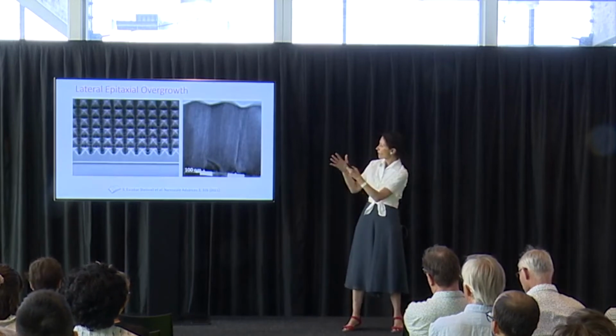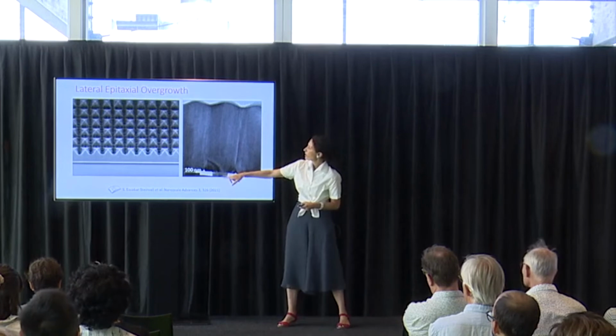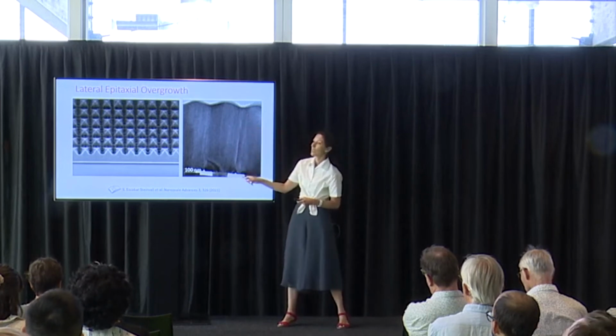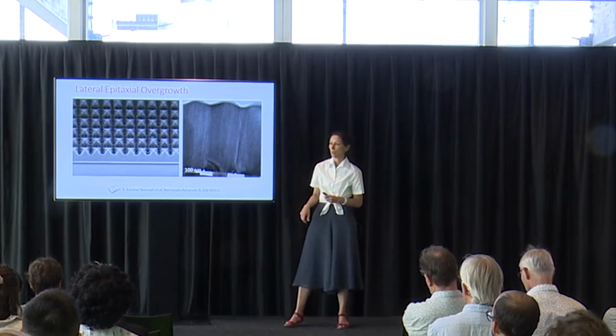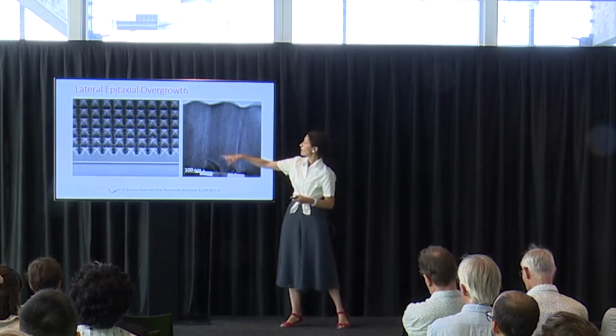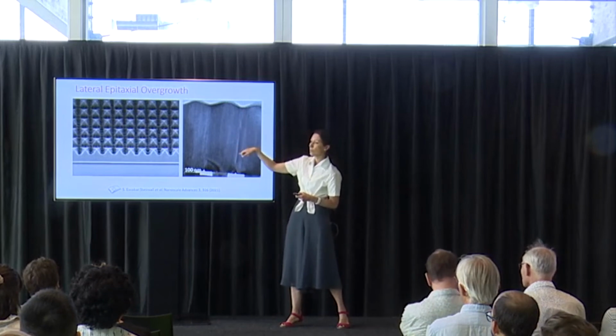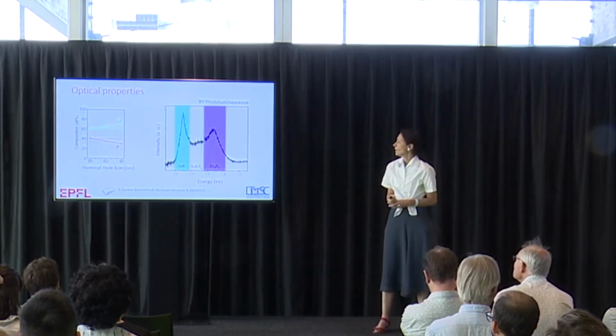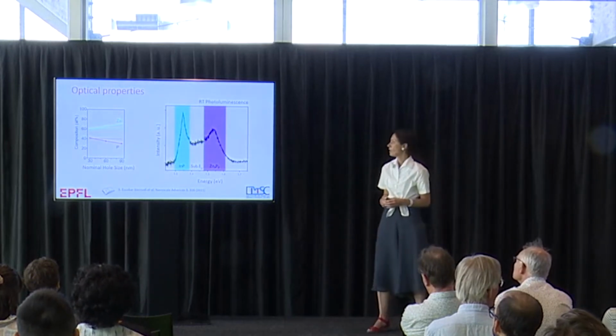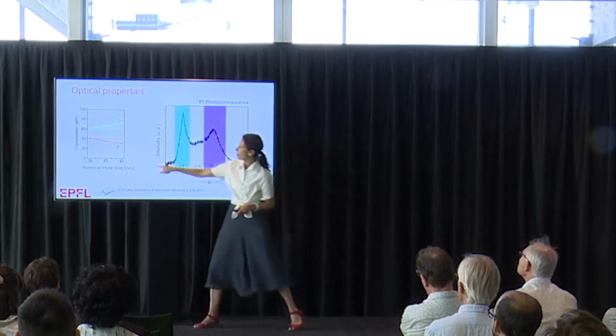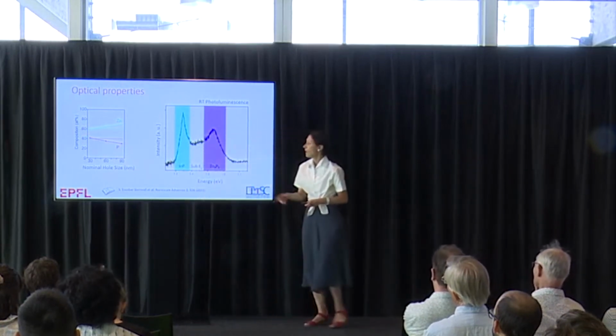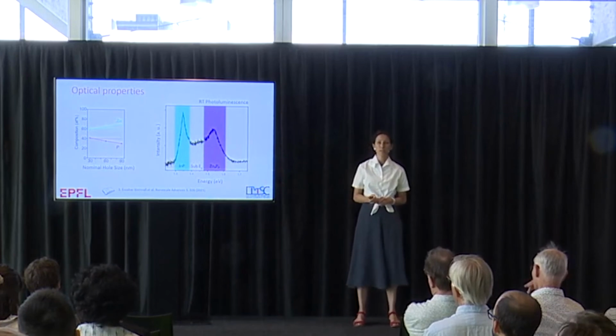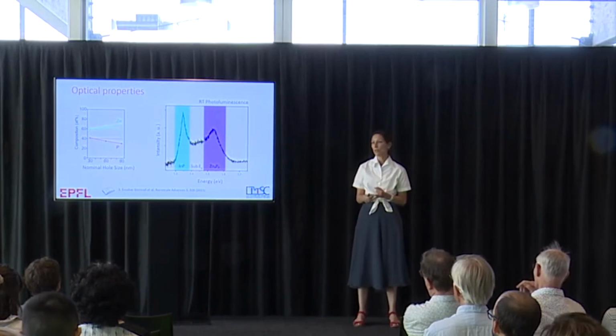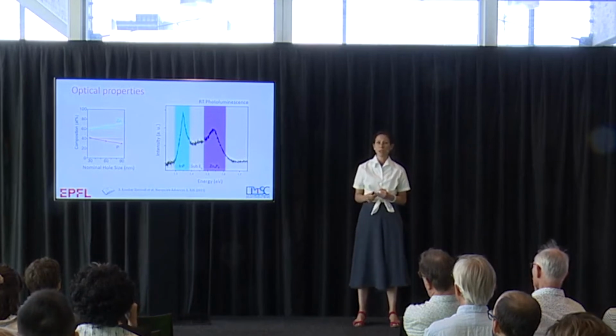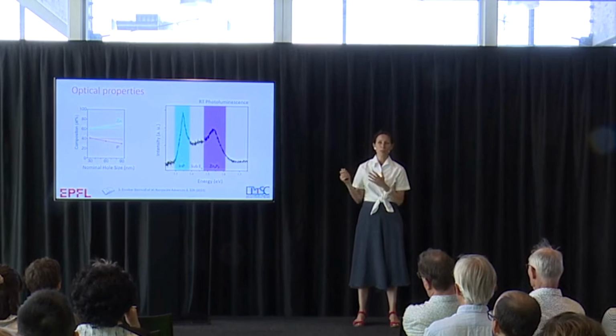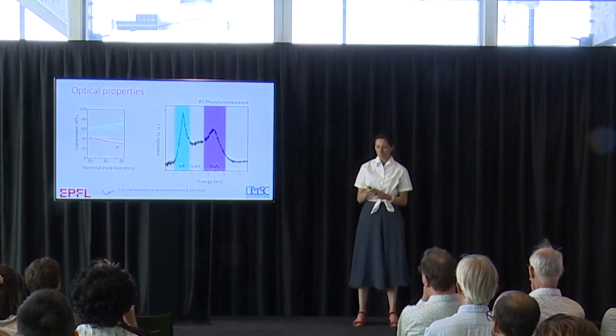If you look at these joined structures, you see that the grain that starts here is single crystalline. You have some grain boundaries here. We think it shouldn't be too much of a problem because the carriers that you recombine have to go through this path and should not come to the grain boundary. Now, if we look at the properties of these materials, we can also change the stoichiometry, as you see here, depending on the size of the hole, and they have room temperature luminescence. The nanowires only have low temperature luminescence, and the growth on graphene only low temperature luminescence. Here, for the first time, we have room temperature luminescence, which tells us that this is the material we need to use for the solar cell, so we are very optimistic.